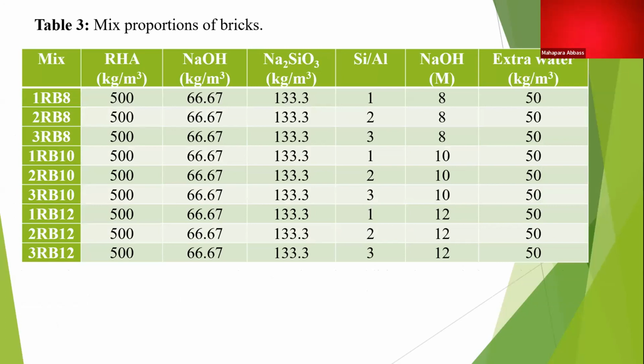These are the mix proportions of the ingredients which were used here. I have followed my own mix design, as I have a publication on that, the rice husk ash based geopolymer concrete optimum mix design. From that, the rice husk ash was used at 500 kg per cubic meter in all the mixes, and these are the quantities of sodium silicate and sodium hydroxide. As I told earlier, I have taken 3 molarities of sodium hydroxide and 3 ratios of silica to alumina: 1, 2, and 3. These are the designations of mixes based on the silica to alumina ratio and molarity of sodium hydroxide.